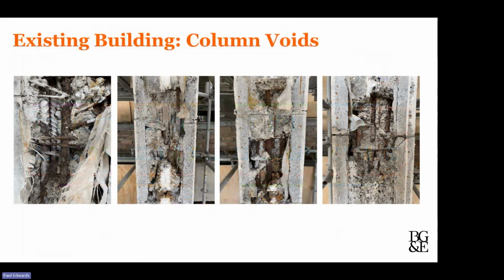There were some other issues which were found due to the non-destructive and destructive testing. So the perimeter columns were formed from elements of precast concrete, which were then infilled. Well, I say infilled, but one common area of concern that was found was actually the infilling of the precast around the columns wasn't undertaken very well. So there are large numbers of column voids found, and you can see some images here of the nature of what was actually found.